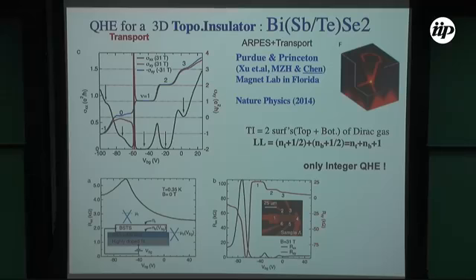Now, if you have sufficiently bulk insulating topological insulators, your transport signal will be mostly coming from the surface, because only the surface is conducting. And if the surface is conducting, it's a 2D electron gas system. So then you should be able to see the Hall quantization. In the transport geometry, both top and bottom surfaces contribute, so your half integer and half integer add up to an integer. So if you do transport, you'll see this integer quantum Hall effect. For that reason, I think when people studied these materials with transport, they never found anything that unusual, because integer quantum Hall is not a new thing.